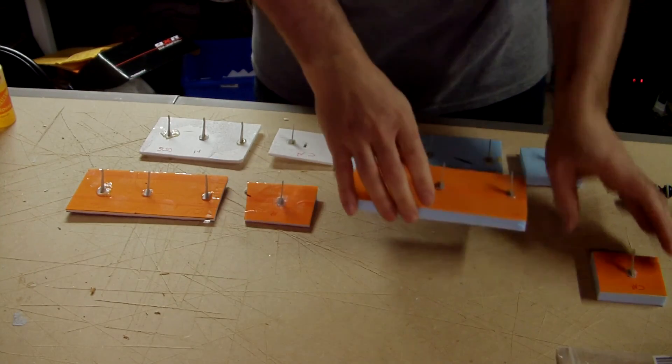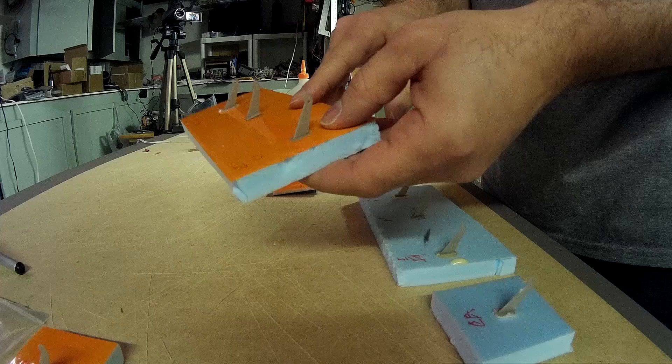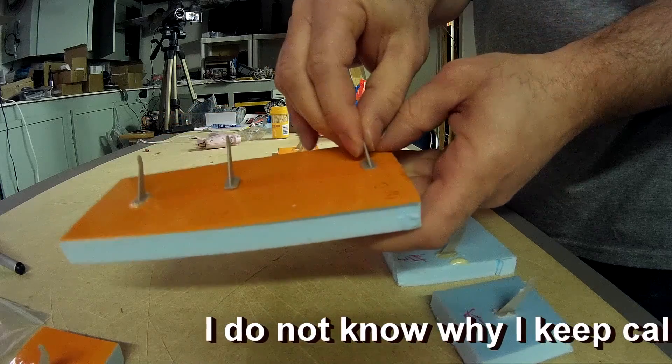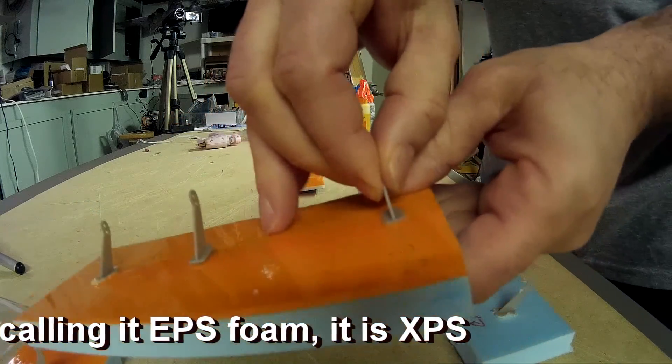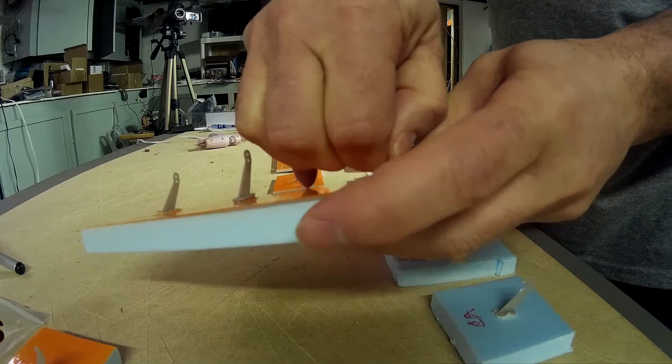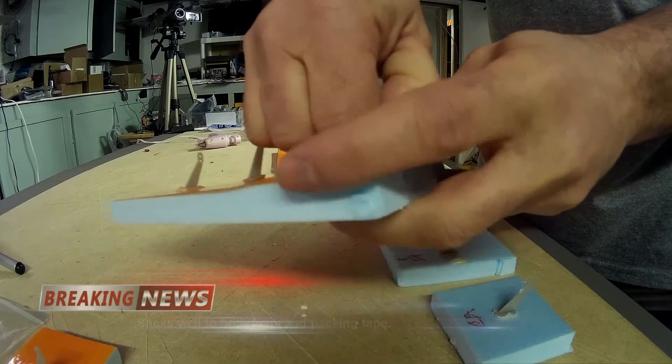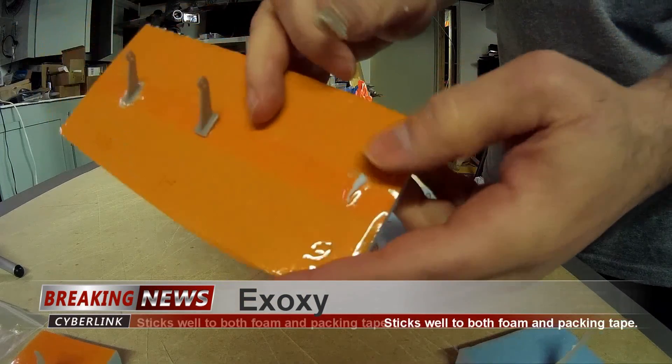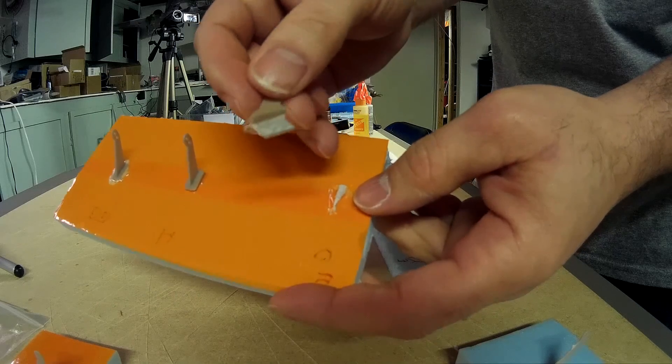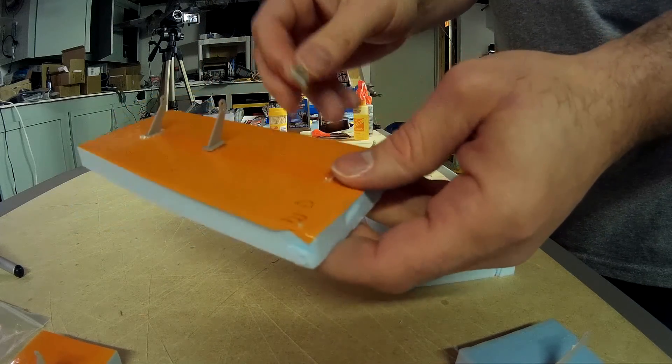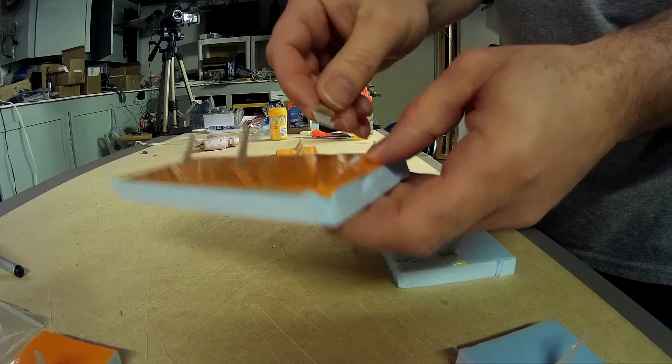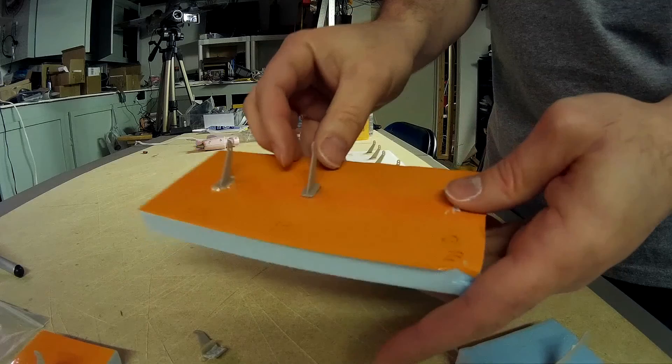We're going to stick with the packing tape on XPS foam. The next I'll try is the epoxy. It's definitely more sturdy than the CA was. In fact, I got to really rip at that. So did you see that? Or you heard it, I'm sure. It actually ripped foam out when I ripped the epoxy. You see how there's more foam on there? This is a good choice. Epoxy, when you have packing tape on XPS foam, that's a good choice. So far that's the front runner.